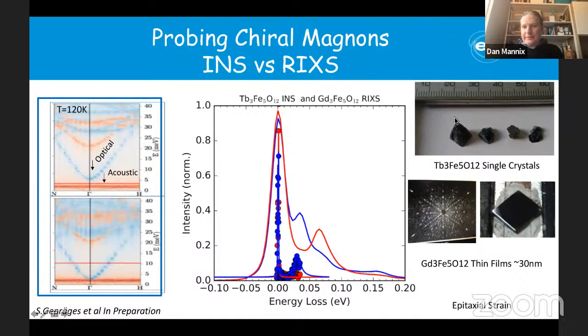What is the advantage of this is that with the neutrons, of course, we have to use very big single crystals to do inelastic neutron scattering. With RIXS, we can apply this in principle to thin films, and even thin films with gadolinium inside. Gadolinium is a very strong neutron absorber, unless you use very expensive isotopes.